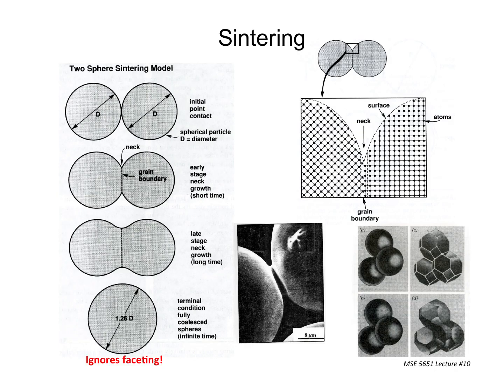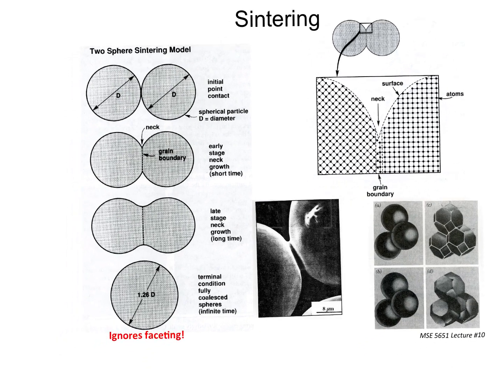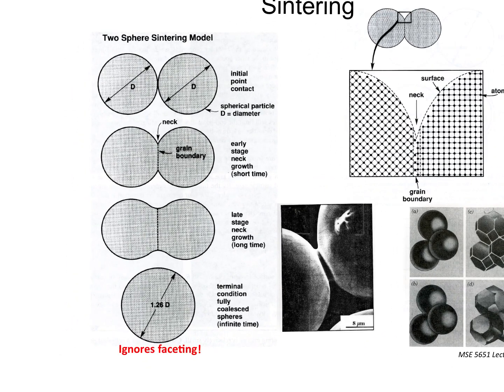And so there's a bunch of different ways of looking at this. And the only reason why I'm inflicting this 2-sphere model on you again is to show you that, remember, they touch, the neck forms, and the grain boundary also forms. If each of these particles is a single crystal, then there's only one grain boundary. If each of the particles is multicrystalline, which is kind of normal actually in the scheme of things, then you have many grain boundaries forming as those necks form. So it may not be just one grain boundary, but the point of this is that this is where I would like to go.